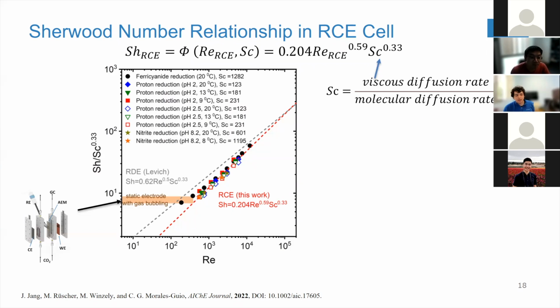Okay, so I just wanted to point out that the static cell, the typical cells that we use, are somewhere here. As we reduce the rotation of the electrode, it starts to plateau, and this is simply because in the background we have this bubbling of the electrolyte, right? And that creates a sort of background convection.